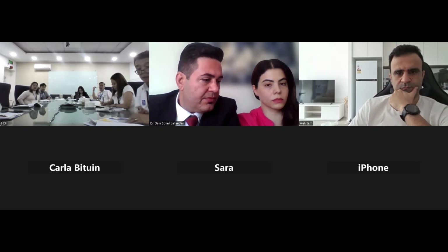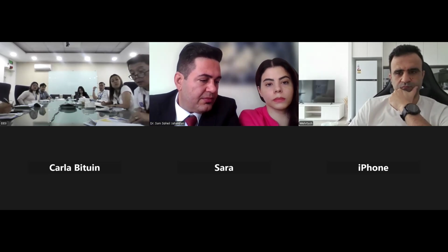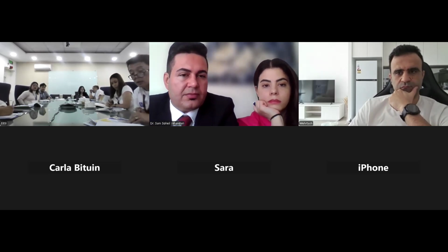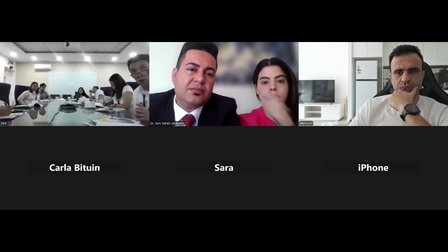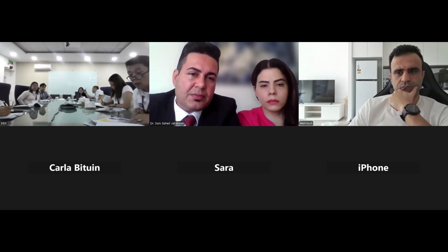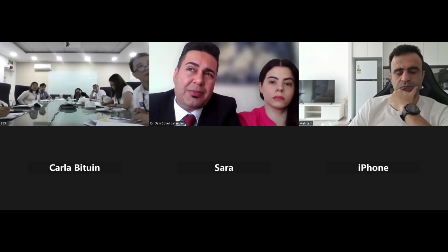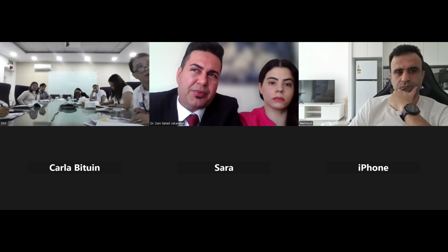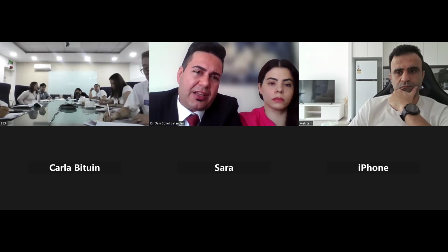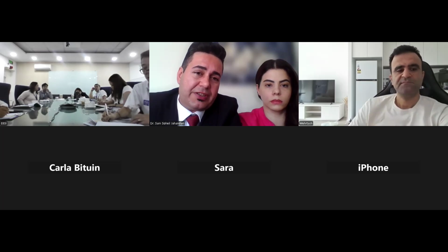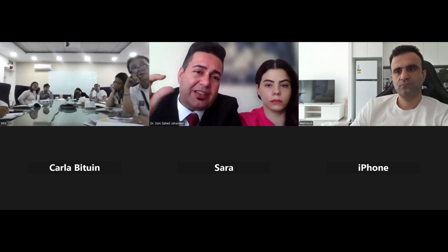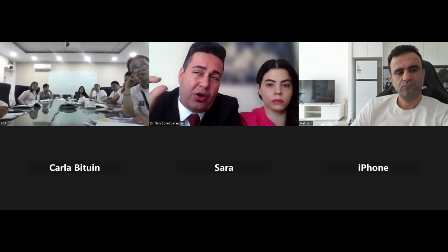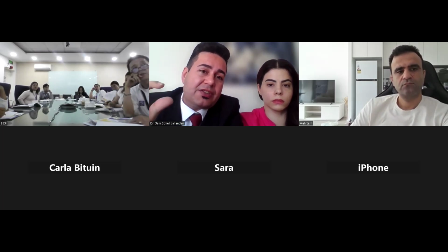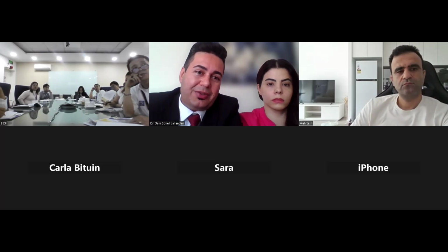Okay, another question. What is the maximum crack width that the concrete with your waterproofing can heal? Currently it's limited to 0.5 millimeter, which is still better than crystalline admixtures or other admixtures on the market. And also that self-healed crack, which is a really important part, would resist hydrostatic water pressure. It's not just healing.